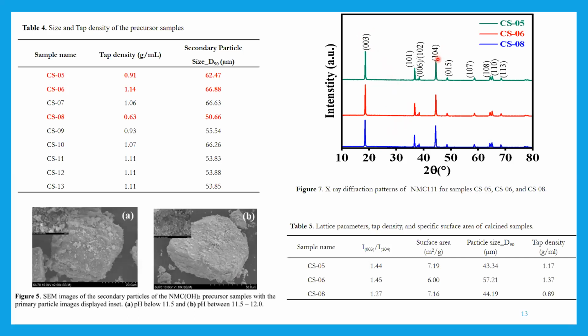And then we also looked at the peaks, the ratio of specifically the 003 peak and the 104 peak. So during addition of lithium, since lithium and the nickel ions have about a similar size in their radius, what can happen is that they switch during this lithiation process. And why this is bad is because when you go to perform the charge-discharge, you will have less lithium available, and hence your performance will deteriorate rapidly over time. And so we found that the ratio to know that you will have better performance is 1.2 and above. And so from all the samples we synthesized, we found that we had a ratio above 1.2.